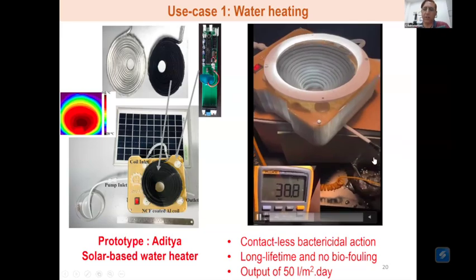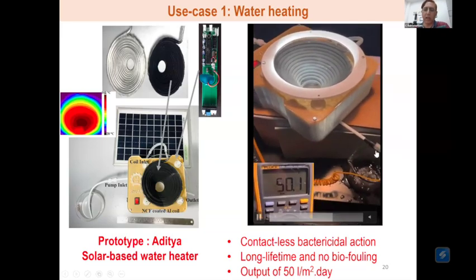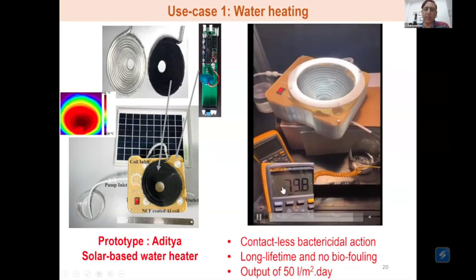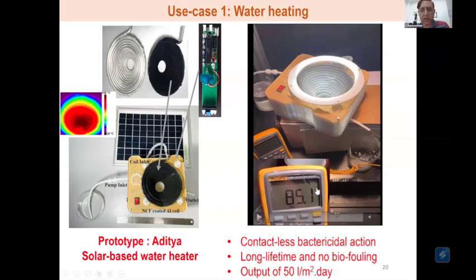If you see, we are measuring the temperature of water at the outlet, and you can see that the temperature reaches close to 80 degrees. In fact, we are able to cross 80 degrees. This is water heating with no other energy but sunlight. And because we are able to cross 80, something interesting opened up.